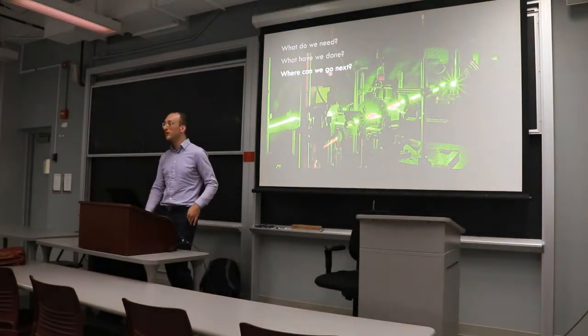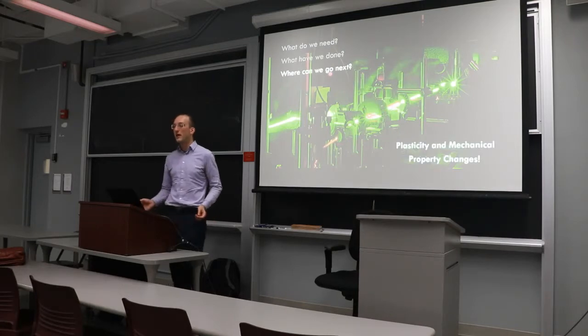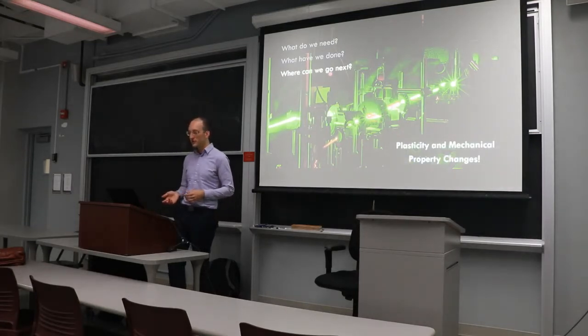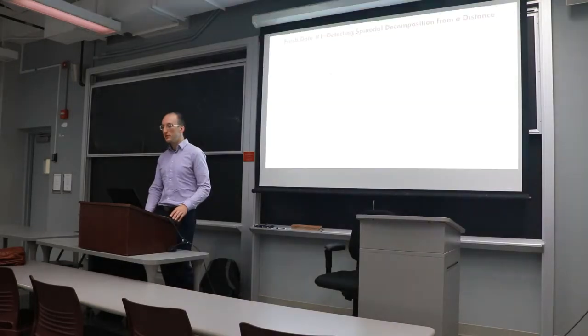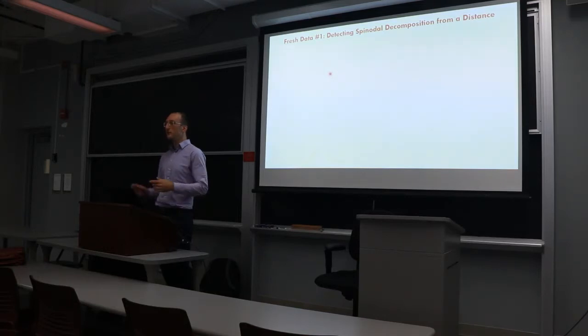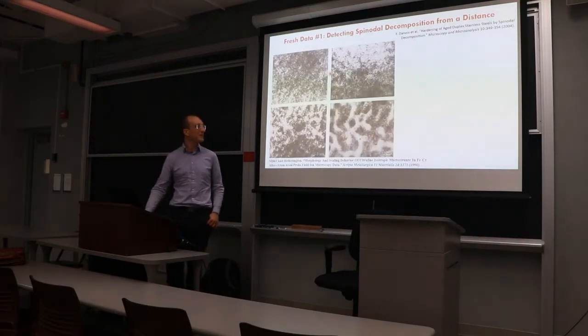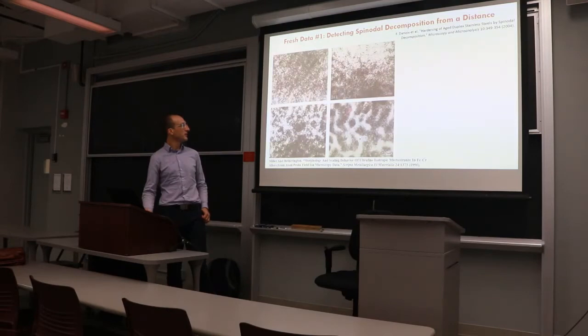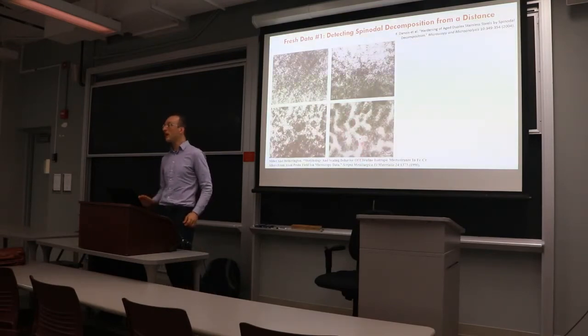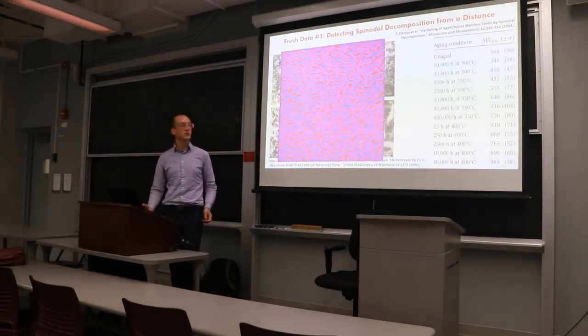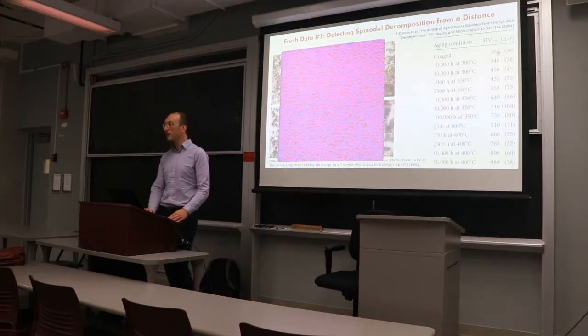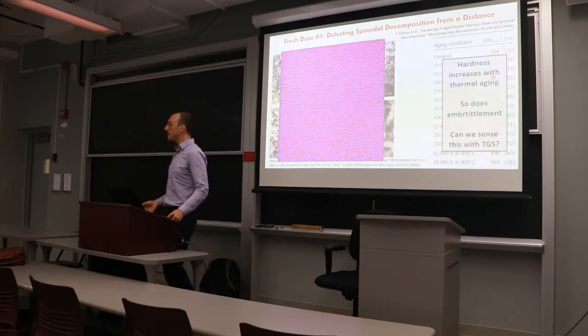Where we're going next with this is beyond single crystals and onto real alloys, like plasticity and mechanical property changes. And here I'm going to talk about something called spinodal decomposition. Is anyone familiar with this process? It's the double derivative free energy region, and I see you nodding, yeah? In the phase diagrams where you can get homogeneous phase separation from a good solid solution into alternating nanometer level laps of a high and a low chromium alloy, for the case of an iron chromium alloy. And this slow and steady decomposition causes a huge increase in hardness and an associated decrease in ductility.